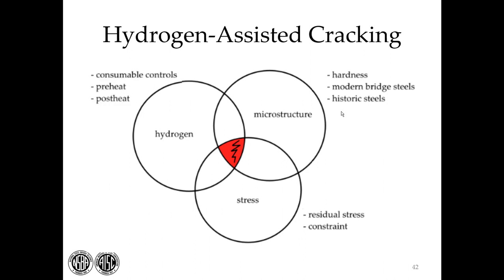The other thing we can control is hydrogen. Hydrogen can come from the consumable, as I mentioned, so we're very careful about how we handle the consumables. We keep coils in containers that are not exposed until we're ready to use them. We put stick electrodes into rod ovens to keep them warm, to keep the moisture off of them. We also use preheat. The code has preheat that is required based on the thickness of the material that you're welding to help drive hydrogen away.